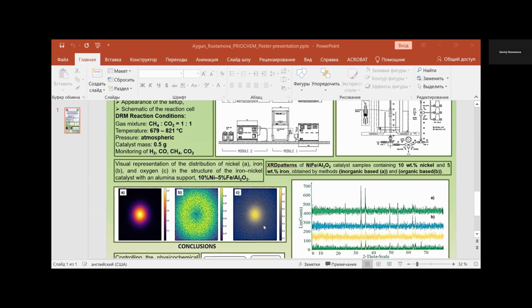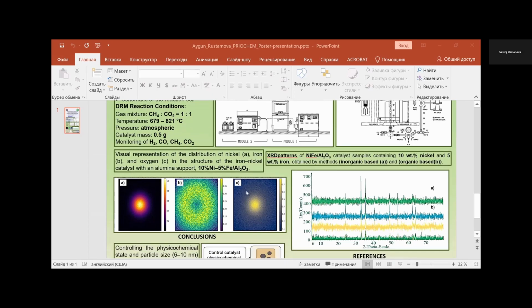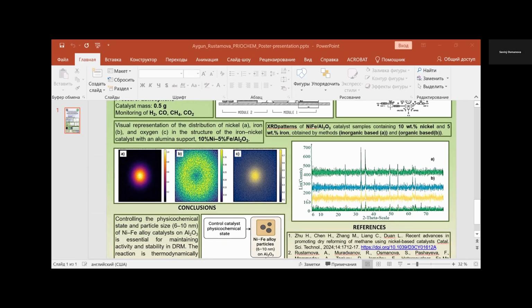you can see that our nickel component is mainly in the center of our catalyst, while the iron is well dispersed around the surface of the catalyst, and you can see the oxygen dispersion, which is the main part of our base structure, aluminum trioxide, and you can see that it is well dispersed by the ferrum, nickel, and aluminum trioxide. And here you can see XRD patterns of our catalyst, and you can see that there